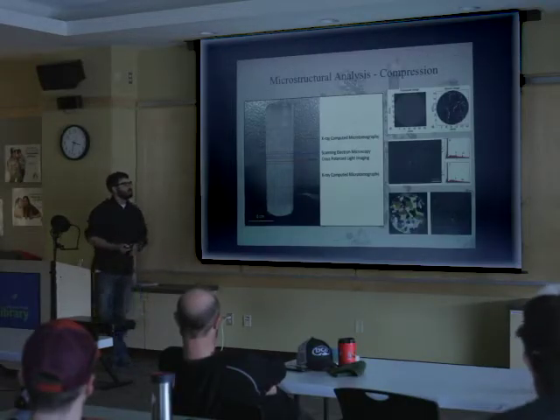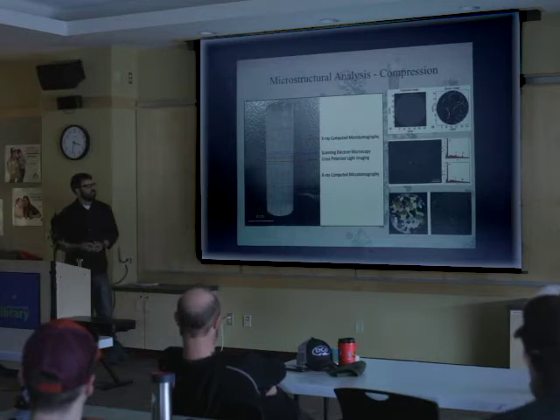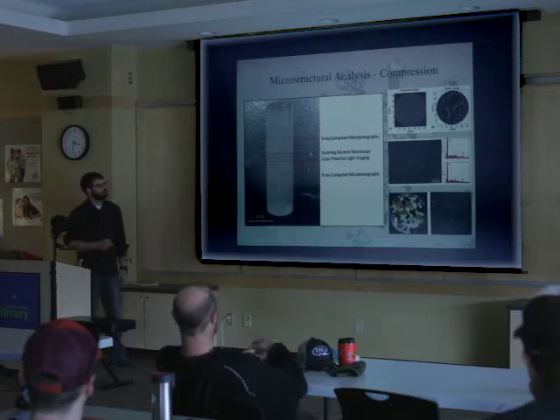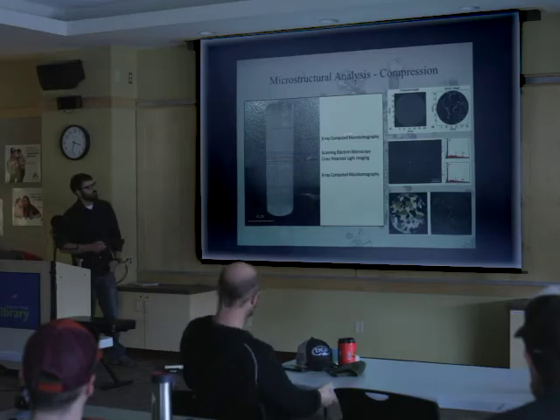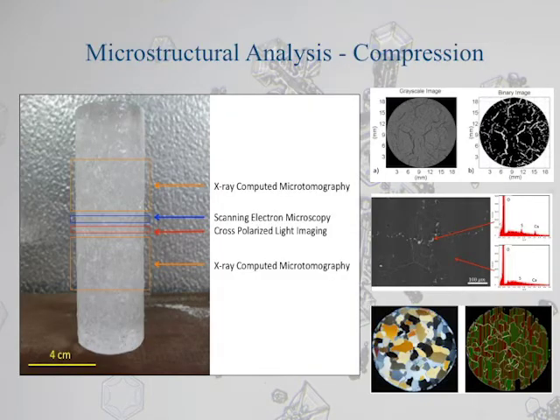After the test, we did a microstructural characterization of each of the samples. So for the compression specimens, we did micro CTs, we used SEM, we did cross-polarized light imaging. I'll show you the results from some of these different characterization techniques.